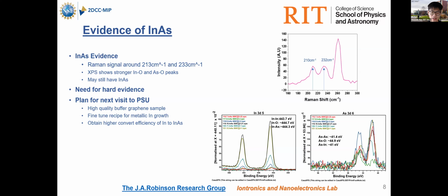cover, overlap with our indium arsenide peak. So that actually weakens our evidence, because if we see oxide, then we might not be able to show that the indium arsenide is fully underneath the graphene, which is the high quality 2D one signal. So that's what I've done during my first visit.